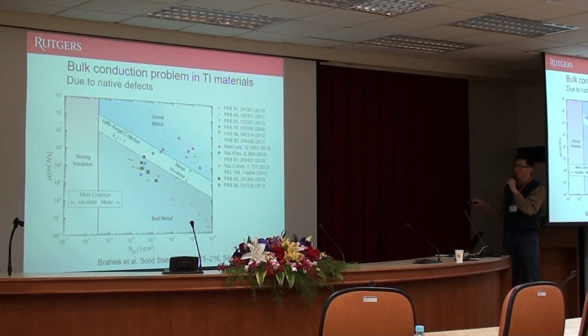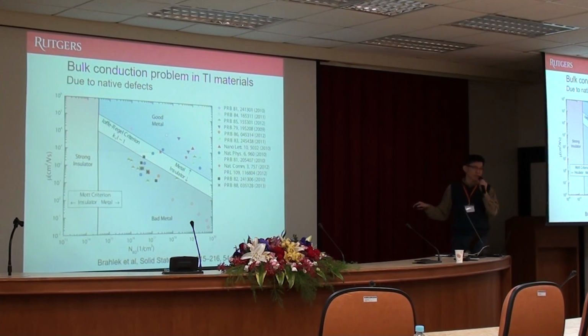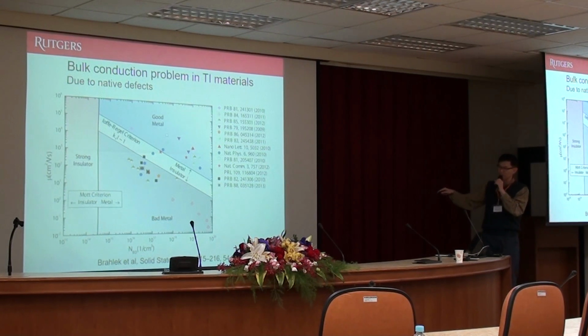If you compare all the literature values available, you can see that the carrier densities are all around 10 to the 16. So this is the 10 to the 14 line. Only if your carrier density is below 10 to the 14 do you really achieve this Mott criteria-based insulator. Otherwise, it's basically always metallic. But there's another method to make them insulating. This is the approach all the people are currently using.